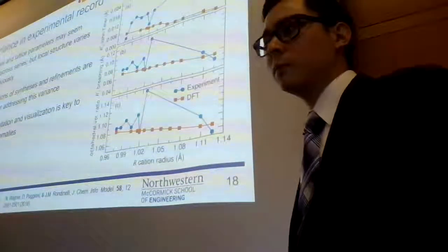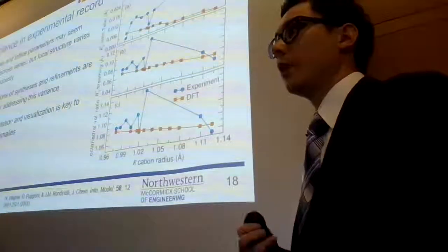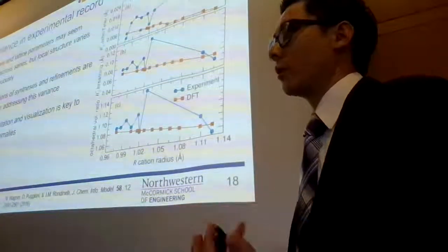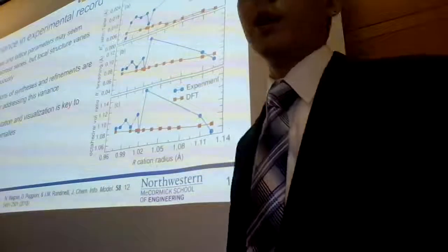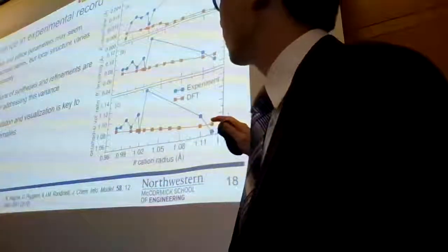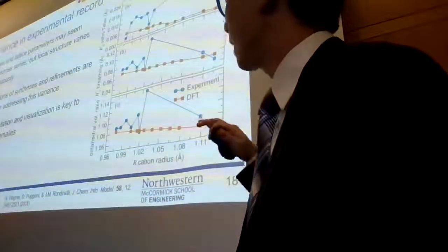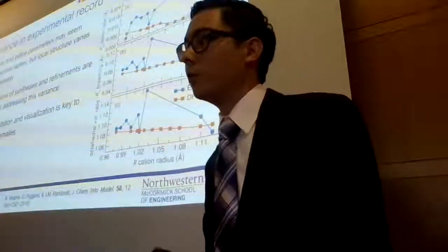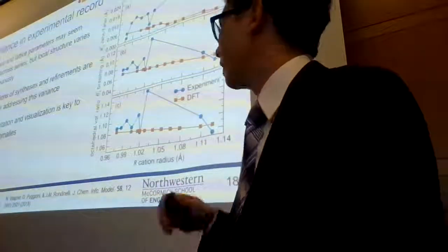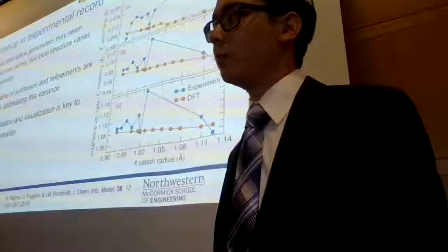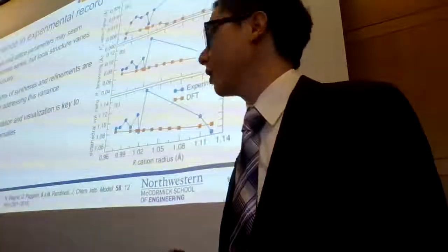it would appear that there's a slight increase because of this outlier for dysprosium. And so actually looking at the structure in a different way, besides the rare earth cation radius or the tolerance factor, allowed us to point out that there was a gap in the experimental literature in terms of the local structure of this family. That made it difficult to just do a simple statistical analysis unless you knew that was the case.